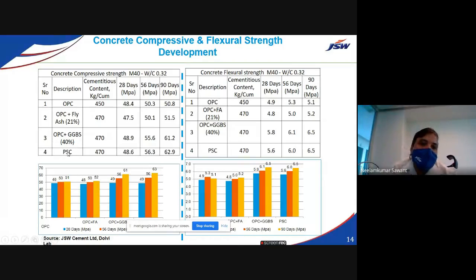GGBS 40%. And if it is a company made product which is already blended at the company side, that is OPC plus GGBS already made, that is called as a Portland slag cement. Definitely it is a controlled quality product. Definitely after 28 days we are achieving the desired 48 MPa strength, and after 90 days we are getting nearly about 62 to 63 MPa. So you can see the difference.